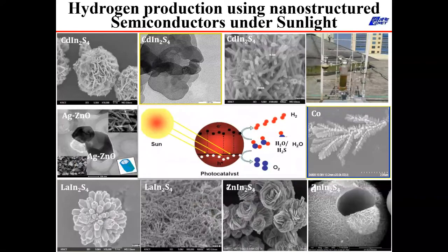I will not show all kinds of materials, but these are glimpses of the materials, like zinc indium sulfide in two forms. One is like this structure. We have lanthanum indium sulfide wires, then very highly crystalline lanthanum indium sulfide structures. Then we doped zinc oxide with silver and found good photocatalytic activity. Then cadmium indium sulfide, we have flower-like structures as well as nanotubes, and nanotubes give better catalytic activity because of good crystallinity and all these things.